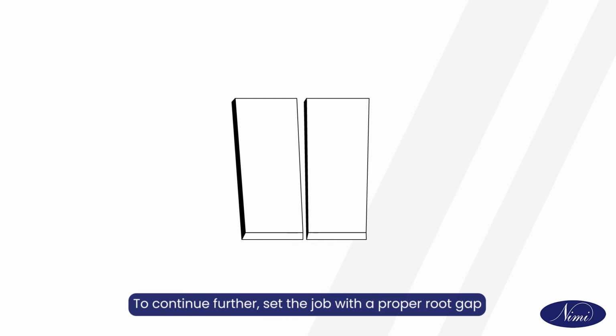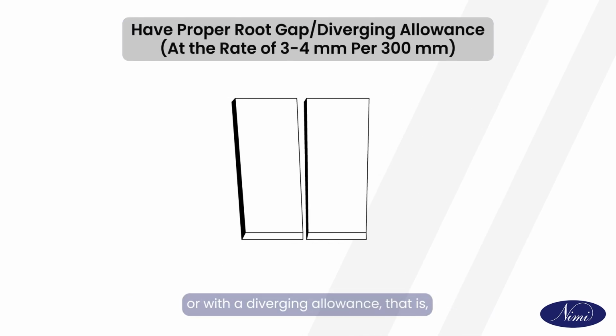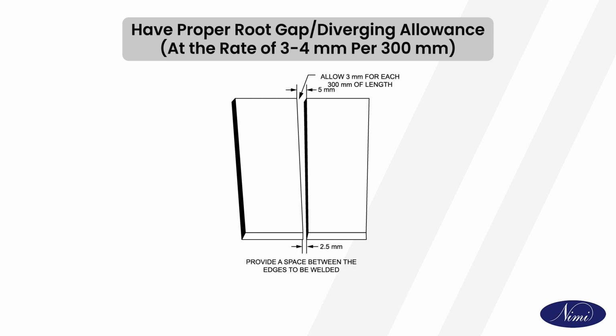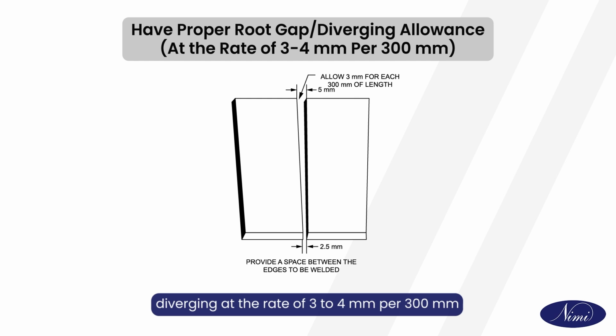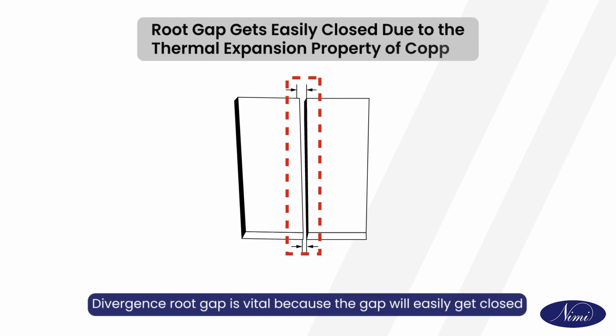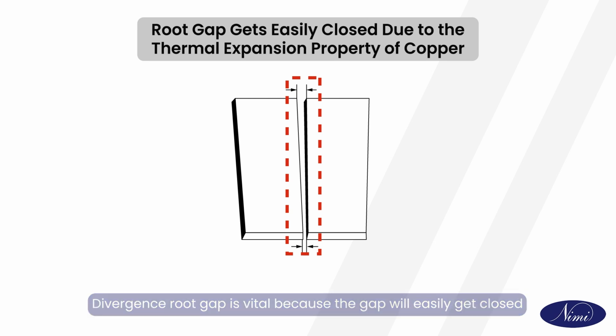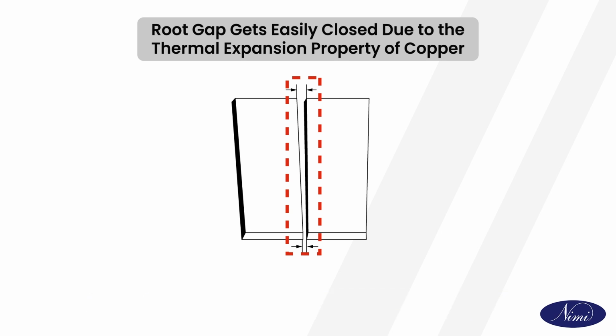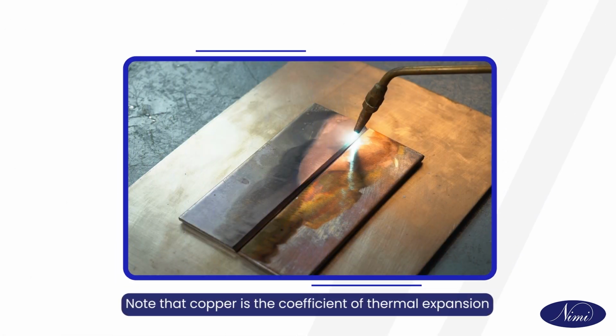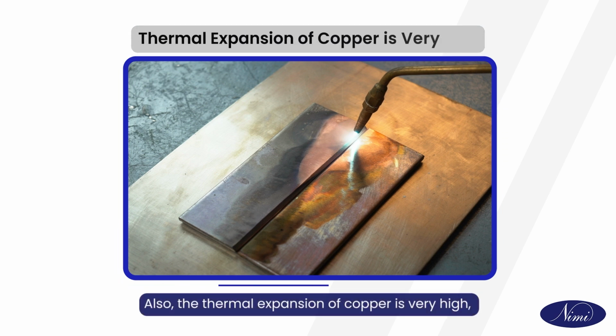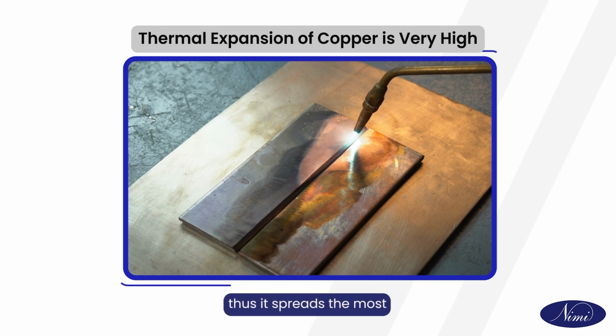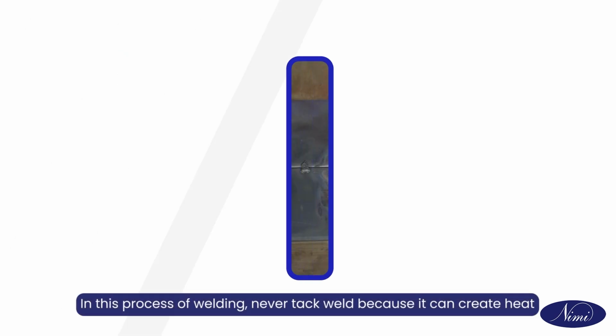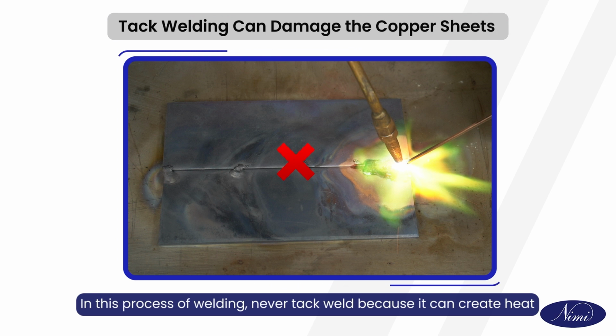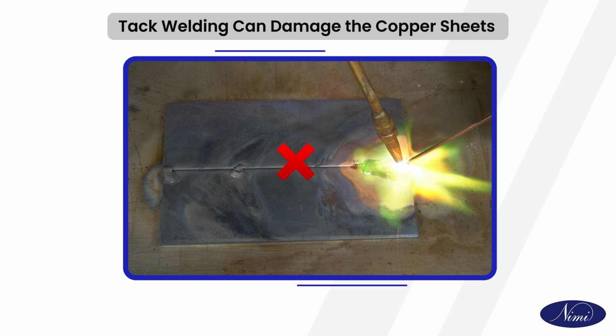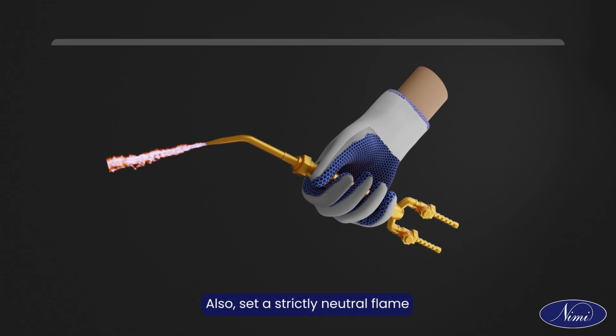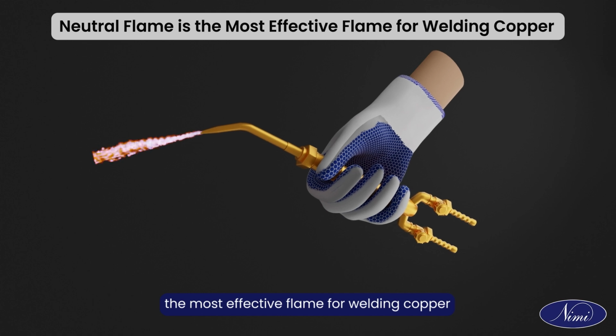To continue further, set the job with a proper root gap or with a diverging allowance, that is, diverging at the rate of 3 to 4 mm per 300 mm. The divergence root gap is vital because the gap will easily get closed due to the thermal expansion property of copper. Note that the thermal expansion of copper is very high, thus it spreads the most. In this process of welding, never tack weld because it can create heat that can damage the copper. Also, set a strictly neutral flame, the most effective flame for welding copper.